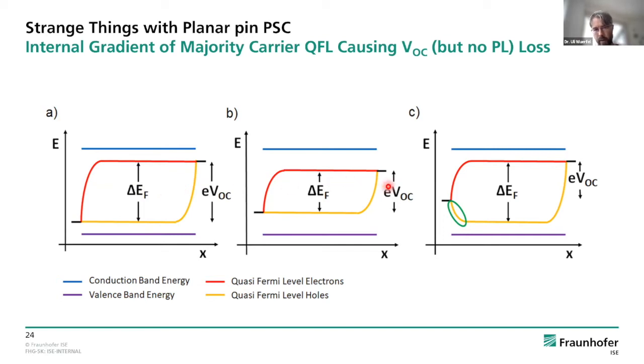You could have a problem with the surface and lose a lot of charge pairs by an additional recombination mechanism, which in principle is avoidable. For example, you choose very bad electron and hole transport materials, which are not very well suited. Then you have a lot of surface recombination. These charge pairs, which recombine at the surface, cannot recombine radiatively in the volume. And due to this additional loss mechanism, you decrease your charge carrier concentrations. It's like, imagine this is a cup. I pour in water, this is the generation rate. I have a small hole here where the water pours out again, but of course, at a certain filling level. This is the steady state, the equilibrium situation. I pour constantly at a constant rate some water inside, and the water is going out here at a certain filling level. Now imagine I drill another hole.